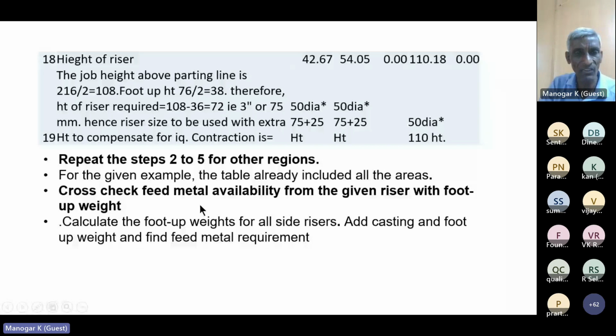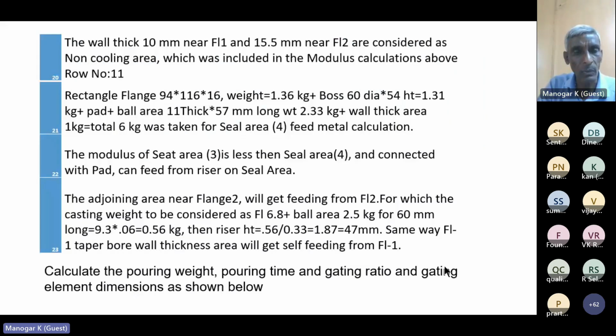Find the weight for all risers, add casting and foot weight, and find the feed metal requirement. The web here will get feed from flange 1, and like that other areas will get feed from the other flange. The rectangle flange will feed the seat area on one side. The modulus of the seat area is less than the seal area, so it will get feed from the top gland area.